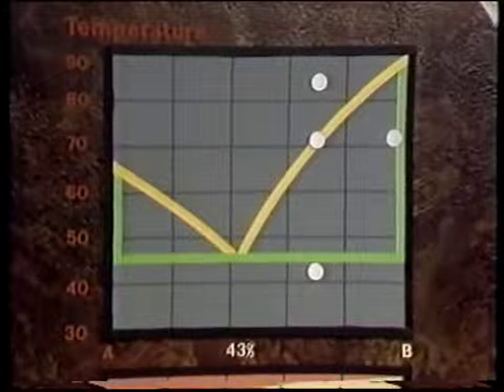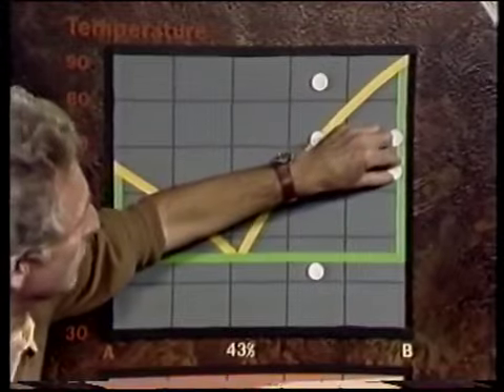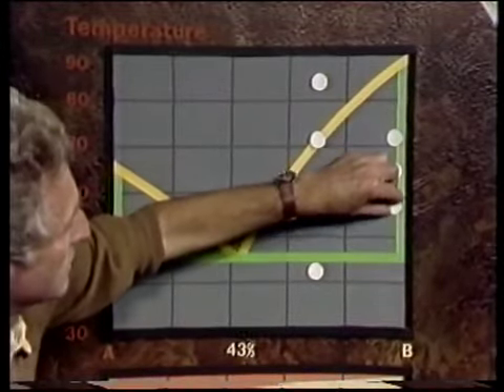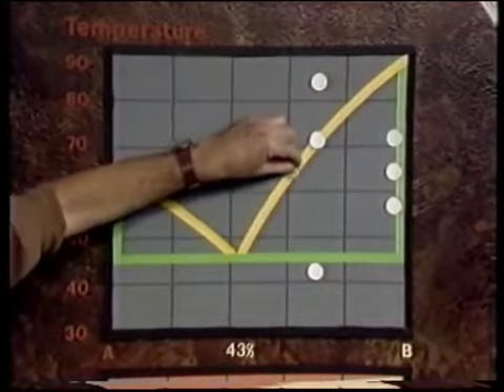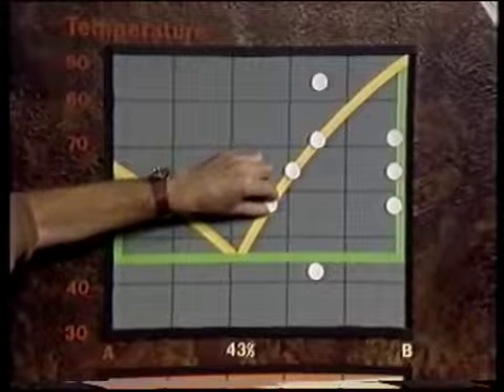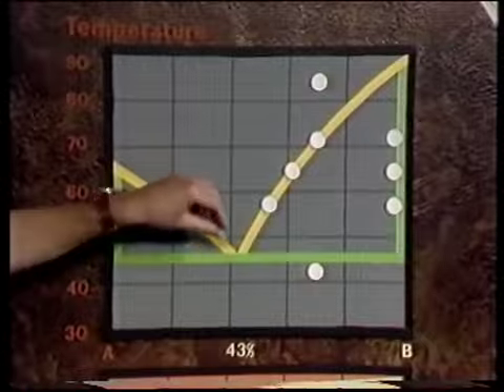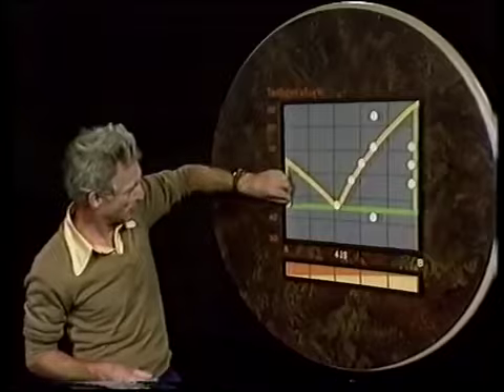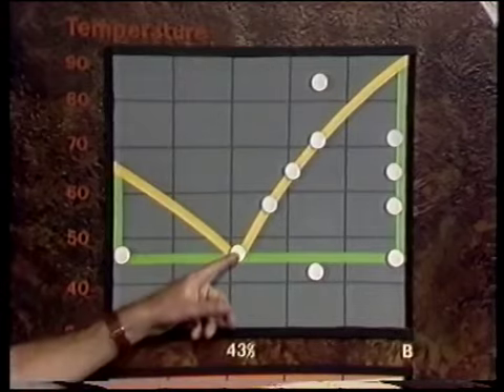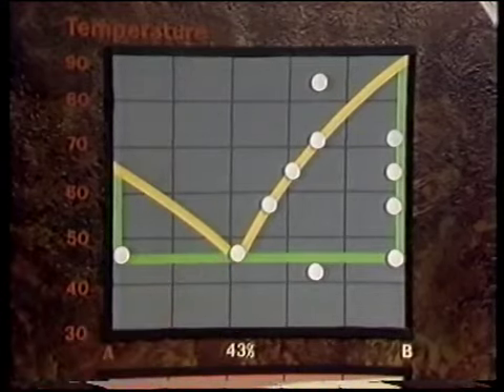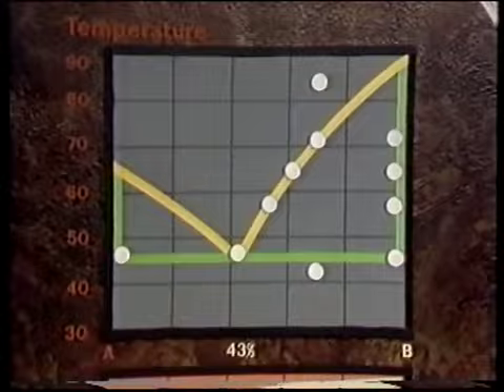That will make the liquid depleted in B, and so as the temperature falls further, crystals of B separate, and the composition of the liquid changes down temperature along the liquidus until it arrives at the eutectic. Now, only at this point can A begin to crystallize from the melt. The liquid can't cool anymore or change its composition. So what's going to happen? Both A and B will crystallize together in the proportions of the eutectic composition and at the eutectic temperature until all the melt is solidified, and only then can the temperature begin to fall again.